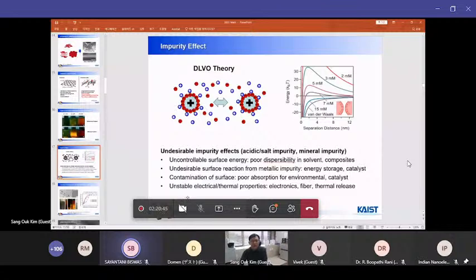And those ionic impurities, including some metallic impurities, can also be critical for further application. Sometimes you have very toxic impurities like acid, so any material based on graphene oxide without purification can be toxic, and it can also be corrosive. If you have metallic impurities, then there will be some undesirable electrochemical reactions, which can be critical for catalyst or energy applications. Those ionic impurities can also yield poorly controllable surface energy, and you also have unstable electrical and thermal properties due to the impurities. So anyway, you must remove those ionic impurities for good dispersibility as well as stable properties in the final